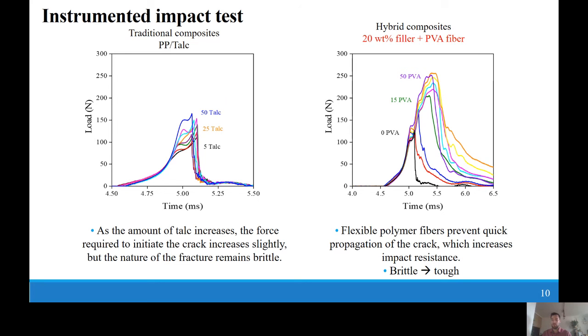When the maximum force is reached, the crack passes rapidly through the cross-section of the specimen. The nature of the fracture in this case is brittle. In the case of hybrid composite, as the PVA fiber content increases, the force required to initiate the crack increases. The crack does not move momentarily, and the flexible polymer fibers hinder the rapid propagation of the crack. The nature of the fracture is tough, even at low PVA fiber content.